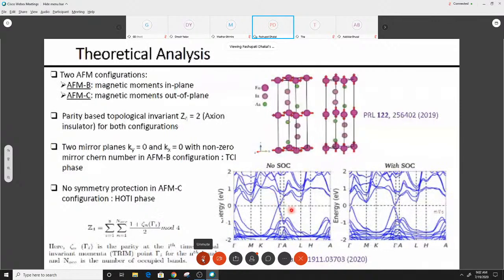In the absence of spin-orbit coupling, the valence and conduction bands dip into each other, thereby creating band inversion at these positions along Gamma-M and Gamma-K. However, in the presence of SOC, the valence and conduction bands are separated, creating gaps. We also calculated the parity-based Z4 invariant using this formula, and we got Z4 equals 2 for both AFM configurations, implying EuIn2As2 is an axion insulator in both configurations.